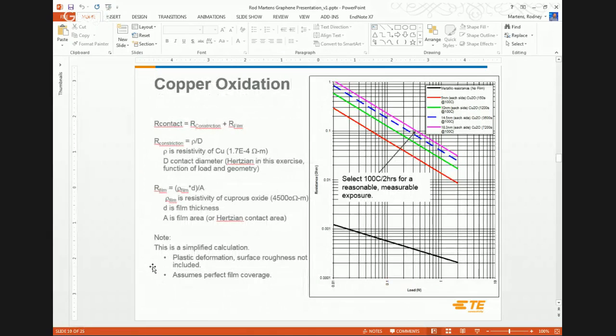The point here was I want to be able to grow a known amount of oxide on a copper coupon. So first of all, I'll clean it, and then I'm going to oxidize it to grow a film on there that's measurable. If it's too thick, then it's an open circuit. We can't measure it. We don't get any signal out of it.